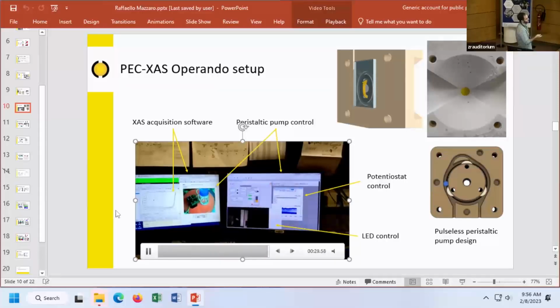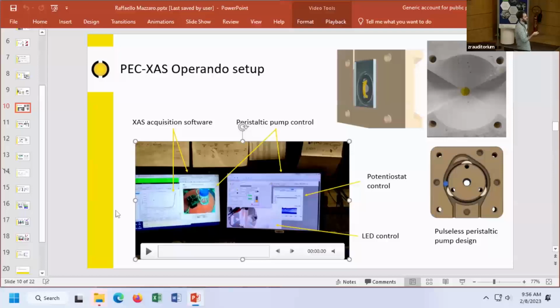And another thing that we designed was a pulseless peristaltic pump designed specifically for this experiment, as basically if we have pressure instabilities, this results in an intermittent bulging of the Kapton window. That's actually a pretty big issue, because that is changing the thickness of the electrolyte, and as a consequence, is changing the absorption coefficient of the element we're interested in.